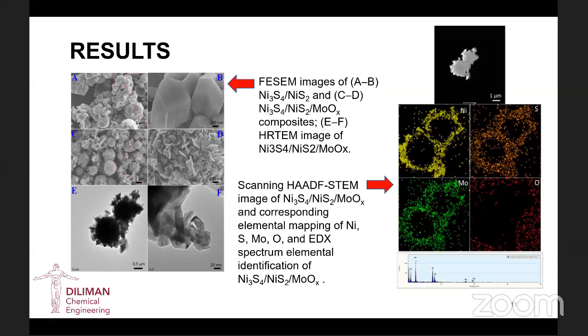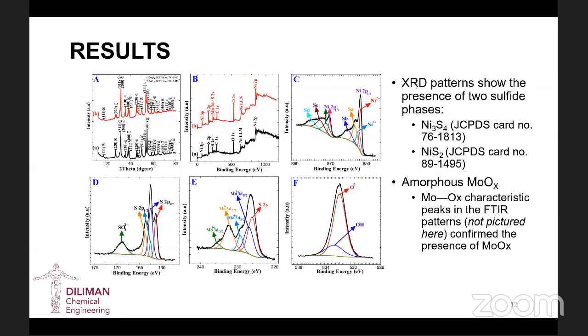And this is important for the analysis of materials with various components. So you can see here the presence of nickel, sulfur, molybdenum, and oxygen on the surface of the material, and the EDX, sorry, it's a little small, but the peaks should represent the presence of the elements nickel, molybdenum, sulfur, and oxygen. So this method is important to show the formation of the compound in the material.